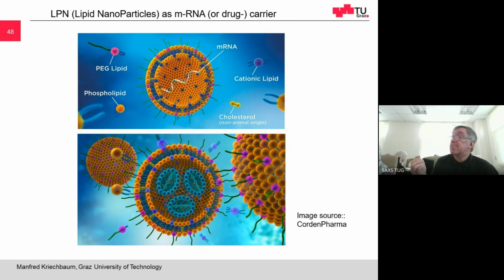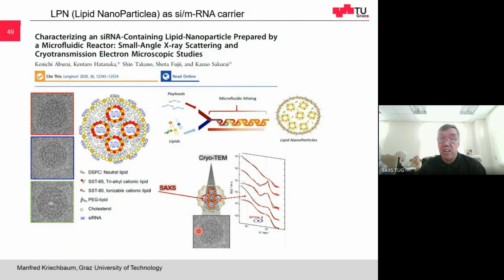And for that SAXS is a very suitable method, because it measures exactly that range, the bilayer thickness, or even the whole diameter of this vesicle is in the range of this method. So there's another application, just an example. You mix your lipids with the RNA with the fluidic mixing device, which makes these lipid nanoparticles which have this payload of the vaccine, and then you can study the quality of your vaccine.